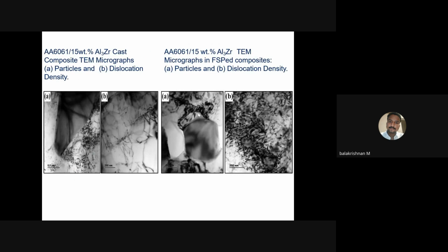Then TEM micrograph. Here we can observe that the particle is very sharp. So we have to break this particle into fine to get more strength. Here the sharp particles in the casted composite was completely overcome by the friction stir processing. While during the processing, the plastic formation and solidification process, plasticity of material and tool stirring force will completely reshape the particle size.